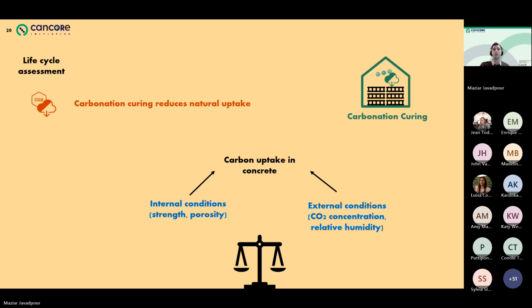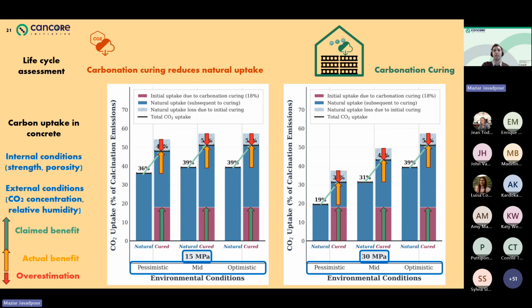So this is just something that we need to take into account. Now, here's what the data and the model that we did actually shows. These two graphs that you can see here are comparing two different concretes that are different both in internal conditions, which is the compressive strength. The bar chart on the left shows the 15 MPa concrete versus the 30 MPa concrete, the higher, stronger concrete on the right. And we can also see the environmental conditions that they're put in as pessimistic, mid, and optimistic. And this is optimistic for the carbonation. So optimistic means exposure to higher CO2 concentration and so on.